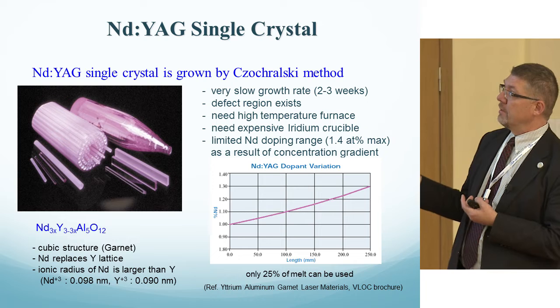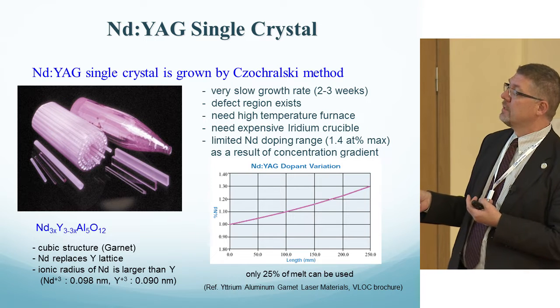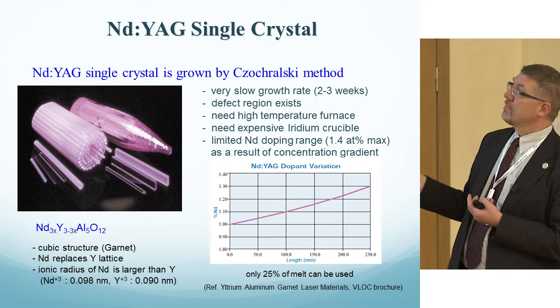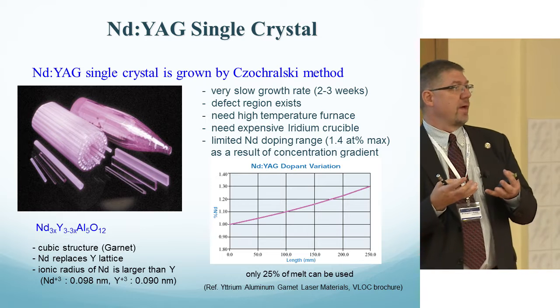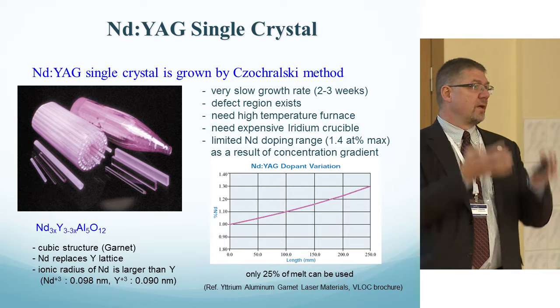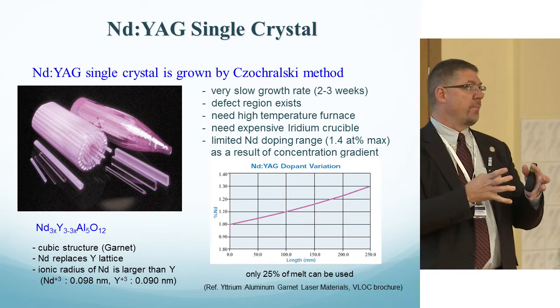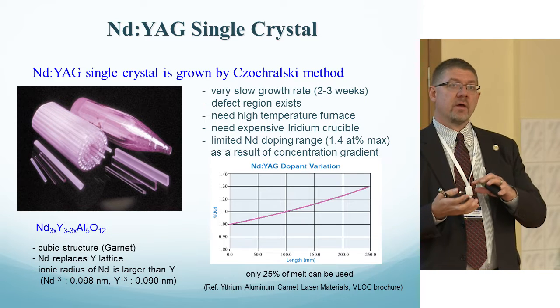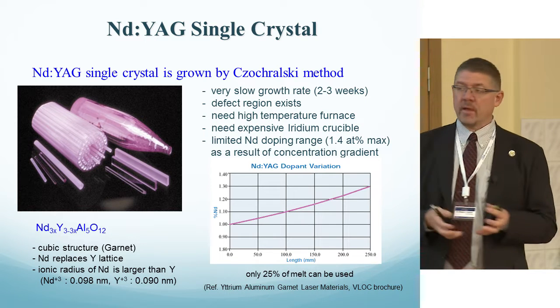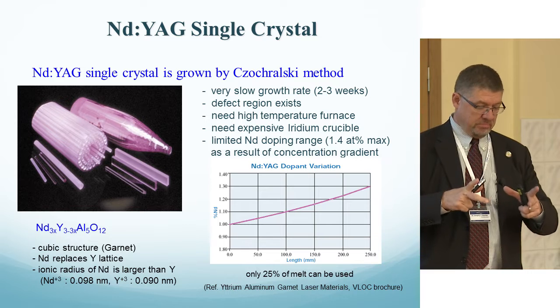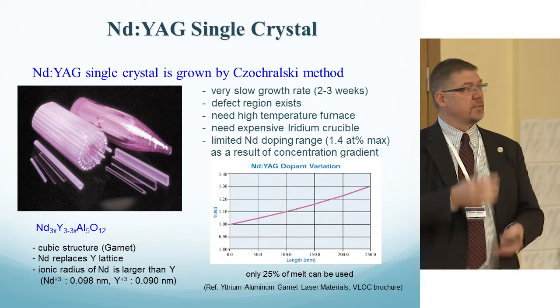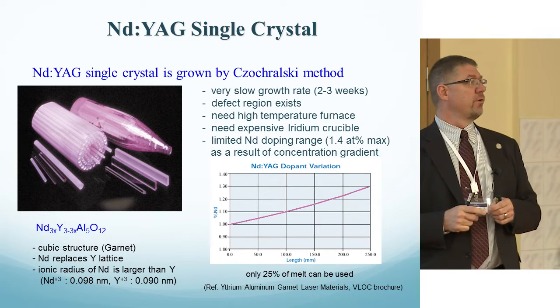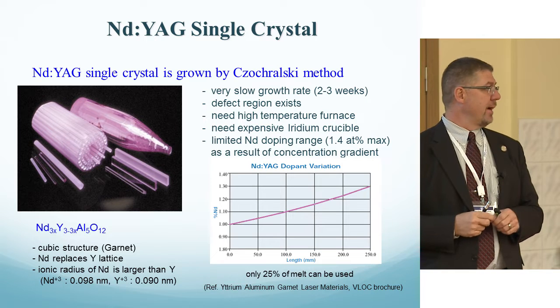You can't get much neodymium in because of the distribution coefficient. And they have to be grown at almost 2,000 degrees, which means most glasses and other materials can't hold the powder in a molten state. So you're using iridium. And this iridium is about this big around. It looks like a paint bucket. And it costs you about $750,000 for each bucket that you buy.